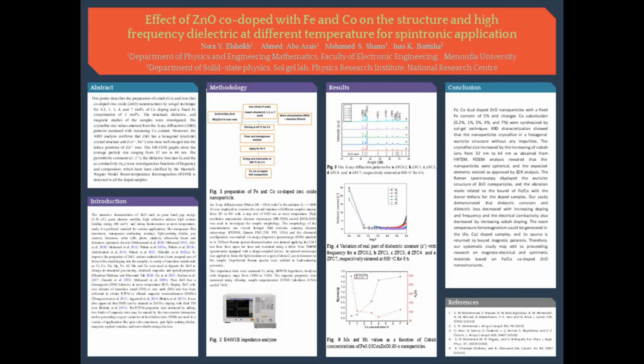We used an E4991B impedance analyzer with a frequency range from 1 MHz to 1 GHz to measure dielectric parameters. The dielectric constant, real part and imaginary part, decreased with an increase in cobalt concentrations. It may be owing to the small dielectric polarizability of cobalt ions compared to zinc. The conductivity also reduced with increasing cobalt concentration. The rise in dopant concentration enhances the concentration of defect ions, which helps the creation of grain boundary defect barriers and obstructs the flow of charge carriers.